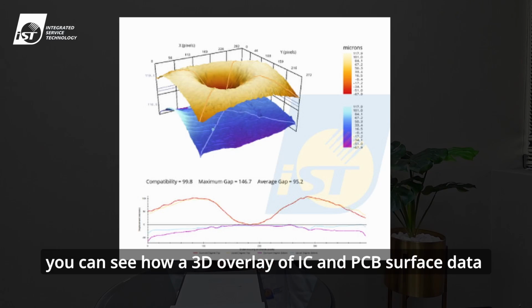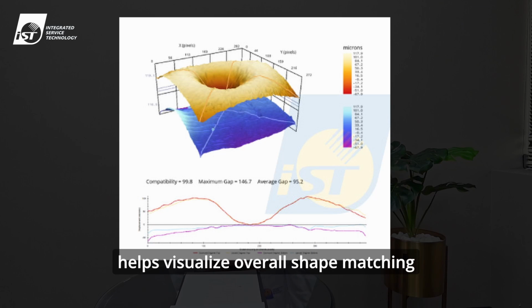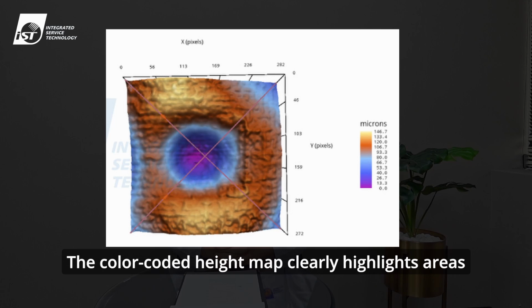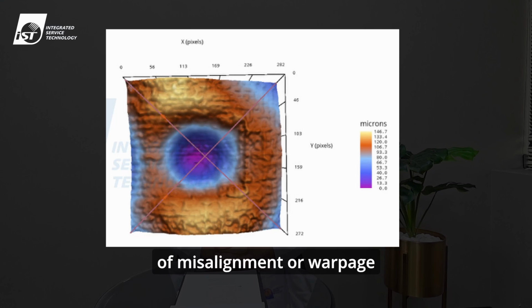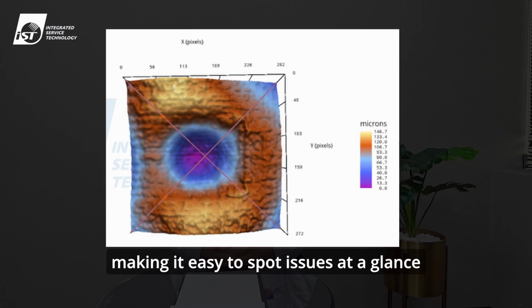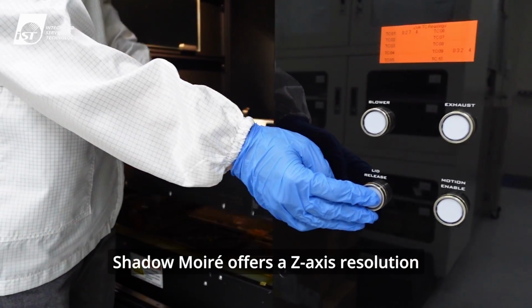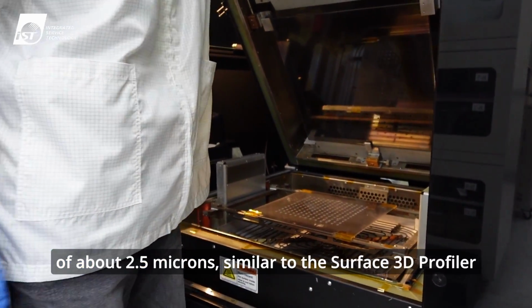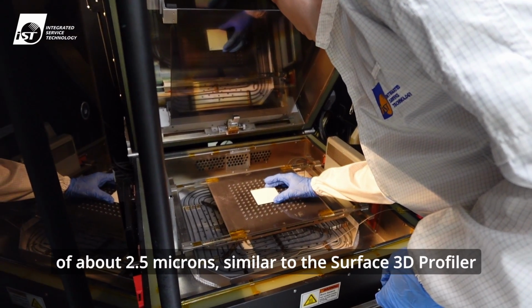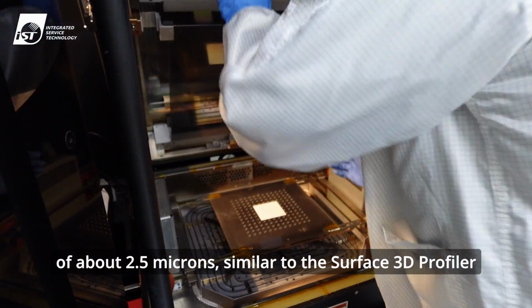In this image, you can see how a 3D overlay of IC and PCB surface data helps visualize overall shape matching. The color-coded height map clearly highlights areas of misalignment or warpage, making it easy to spot issues at a glance. Shadow Moiré offers a z-axis resolution of about 2.5 microns, similar to the Surface 3D Profiler.